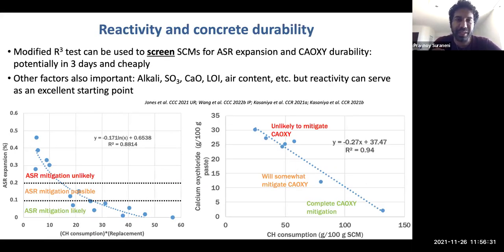Exactly the same thing happens when you consider durability. So we've shown now several relationships between ASR, calcium oxychloride, and reactivity. But you want to be careful because there are also a lot of other factors that affect durability, which are independent of reactivity. As an example, we show here that if you take a whole bunch of different materials and you multiply their calcium hydroxide consumption by the replacement level, you get this sort of relationship, a logarithmic relationship.